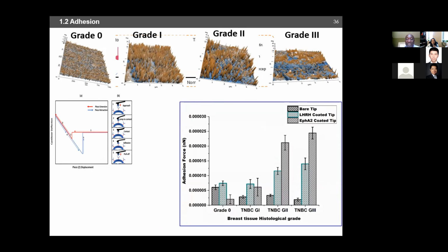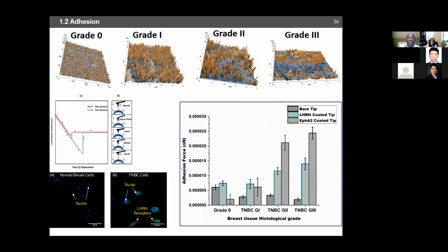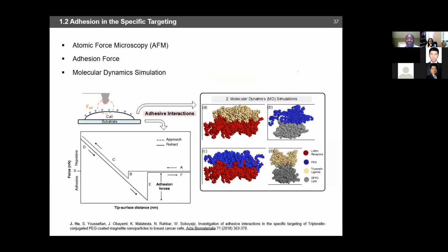And as you look at the adhesion forces, you also see that the adhesion forces increase significantly as you go from grade 1 to grade 2 to grade 3. And so what that basically tells us is that the adhesion forces can be used as biomarkers for the classification of these tumors over and above the other methods that are used currently.